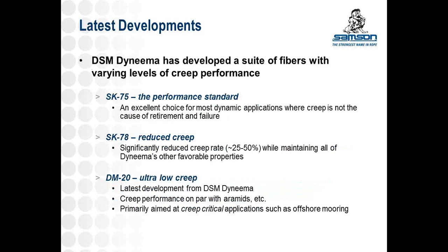So, what can we do about this if we say we want to use Dyneema? Dyneema is the best fiber to use for our particular application, but we may have a concern with creep. What are our choices? Well, SK75 fiber is kind of the performance standard. This is the fiber that we use in Amsteel Blue. And like I said, it's an excellent choice for all-around use for dynamic applications where creep's really not going to be the primary cause of failure. If there is a scenario where creep is of a concern, DSM has a second fiber called SK78, and this is their reduced creep fiber.